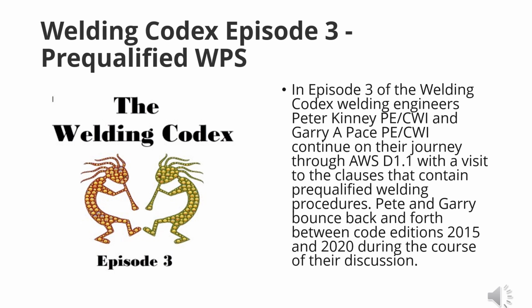Well, then you go up to Group 2. It's more or less Group 1, but it's just a little more difficult. There's some things that might go wrong here. It's a little stronger material, but for the most part, you're still in the shallow end of the pool. You're not really seeing weird preheats and whatnot. Well, then you get to Group 3 materials, and with the Group 3 materials, it's a little more difficult to weld. The weldability isn't as great, and like Pete said, your tensile strengths are starting to climb up here, and by the time you get to Group 4, you only got 3 or 4 materials in there that can be pre-qualified. Yeah, there's only 3 in Group 4.